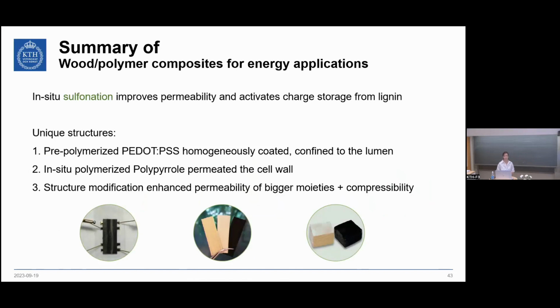So to summarize this part, we could see that sulfonation for all of this material was very important to activate the wood structure and put it more in contact with the conducting polymer. We also achieved very different morphologies in the different studies. We had a thin layer coating the lumen surface in the first case. Then we were able to infiltrate and permeate the cell wall by starting with smaller molecules, while in the last case, we also permeated the cell wall, but instead of using smaller molecules, we actually modified the wood itself, which also showed additional properties such as compressibility.